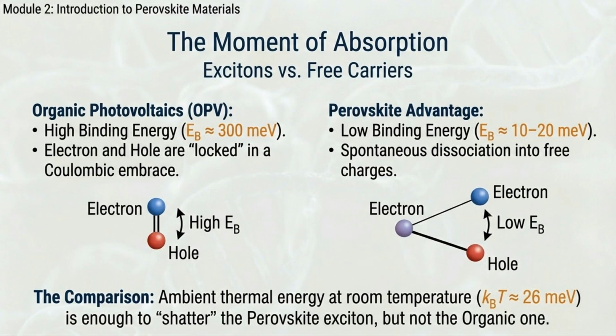Now look at the right side of your screen, the Perovskite advantage. Perovskites behave entirely differently. In a standard metal halide perovskite, the exciton binding energy is exquisitely small, only about 10 to 20 millielectron volts. Why is that specific number so important? Because we must compare it to the ambient heat of the environment. At standard room temperature, the ambient thermal energy of the universe, calculated as Boltzmann's constant times temperature, provides a continuous kinetic background vibration of roughly 26 millielectron volts.